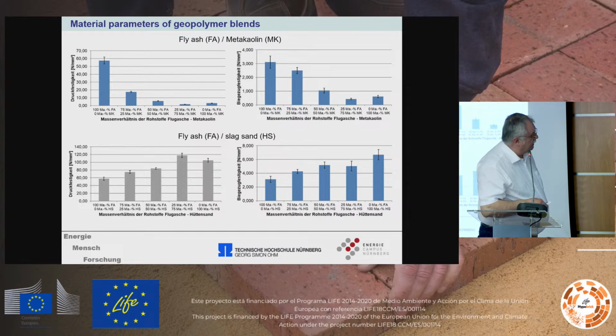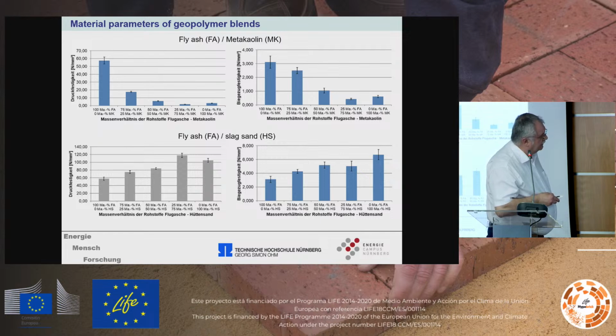Some examples of the compressive strength and the bending tensile strength. The compressive strength you see on this page, and here we have done mixtures, 100% fly ash, and then we go down with the fly ash to 75%, 50%, and so on, 0%, but 100% metakaolin, and you see the compressive strength is going down, and the bending tensile strength did the same. And with this mixture, we use fly ash and slag sand. You see the compressive strength is growing, and the bending tensile strength is growing too. We have here the same mixtures.